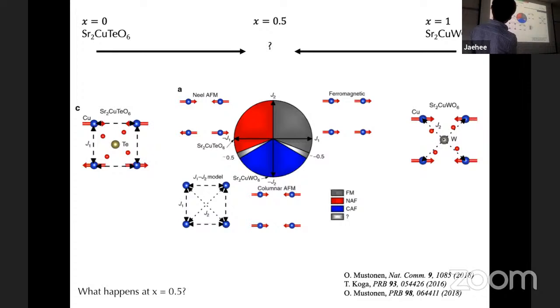All right. So when we have 100% tellurium, then J1 is very strong. Then you have this nice Neel state, experimentally as well, and theoretically it is also proven. If we have tungsten, then J2 is strongly antiferromagnetic. That's why we have this stripe order. But now, if we mix tellurium and tungsten, then the long-range order at the two endpoints quickly disappears,